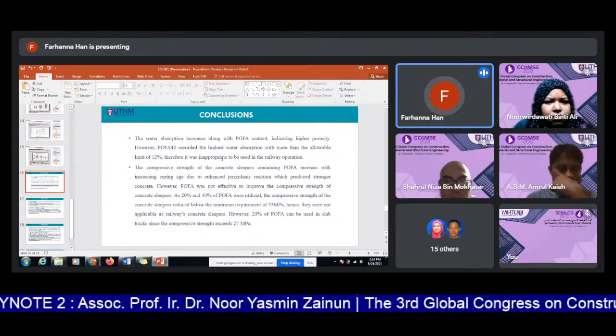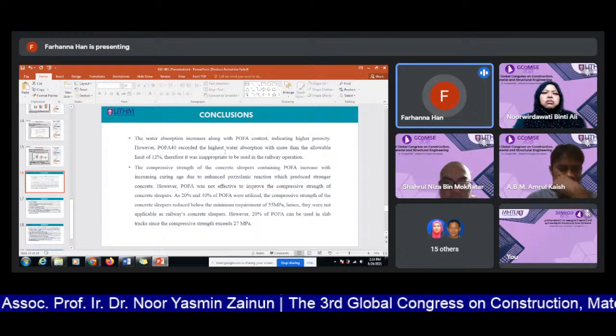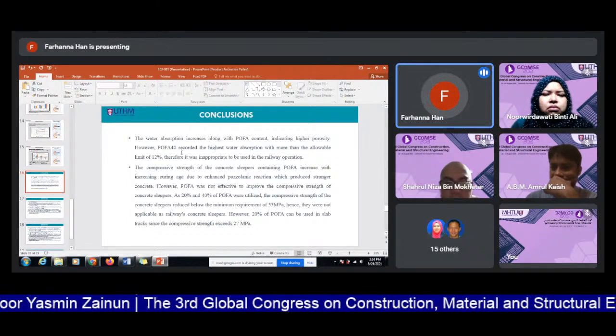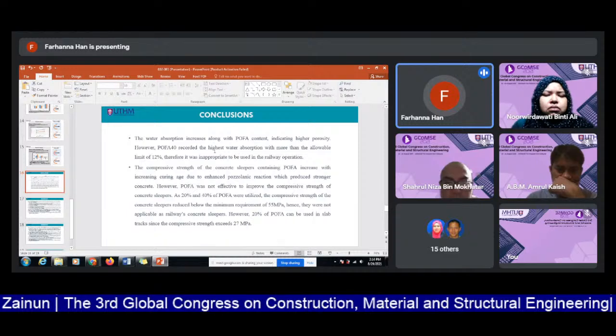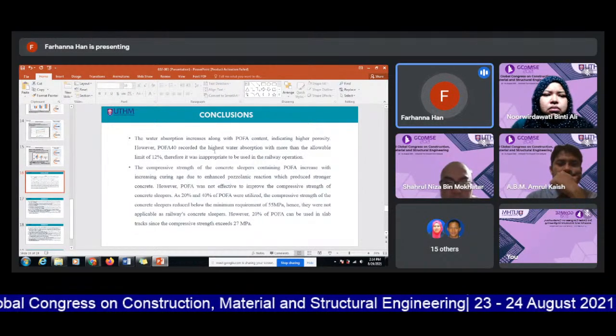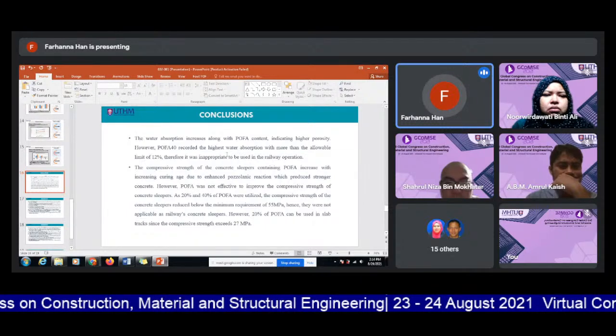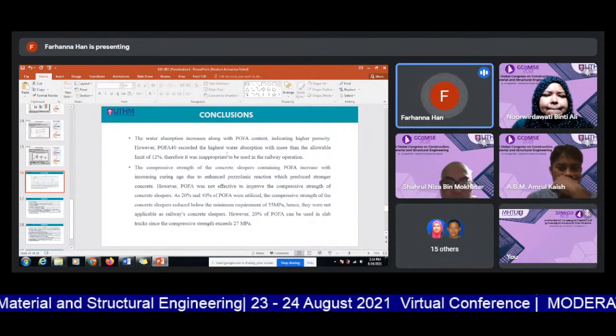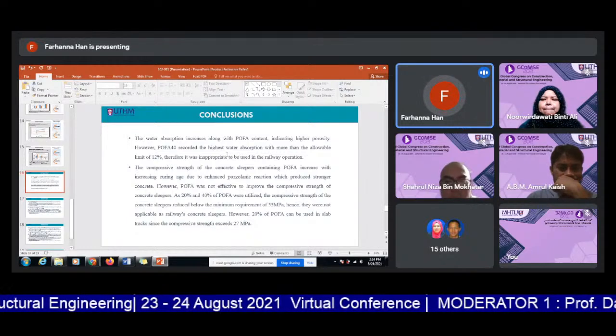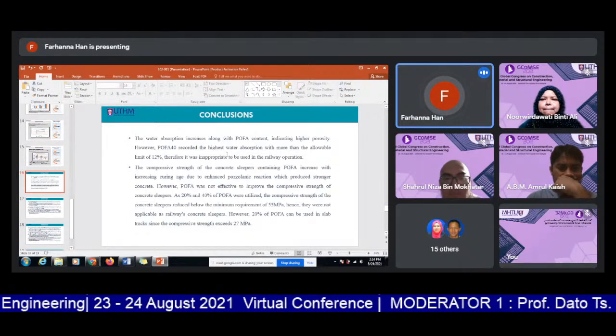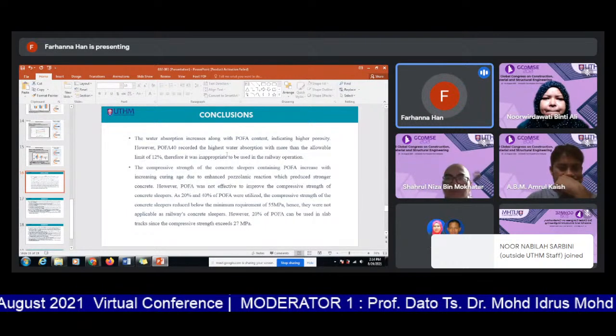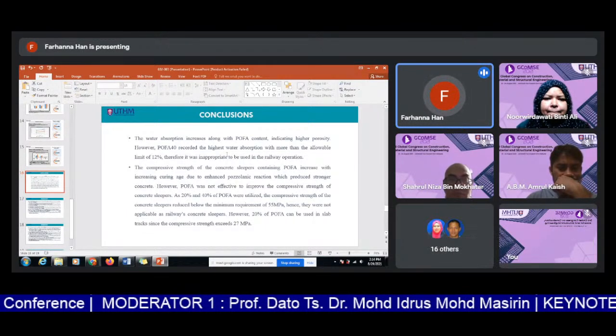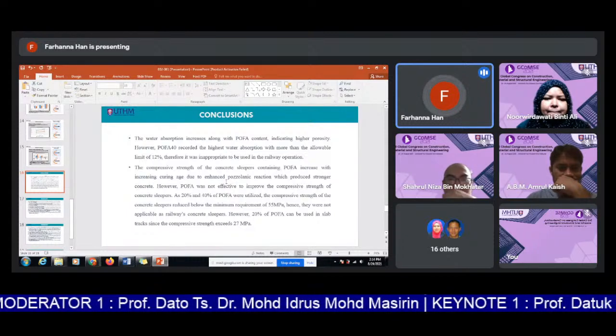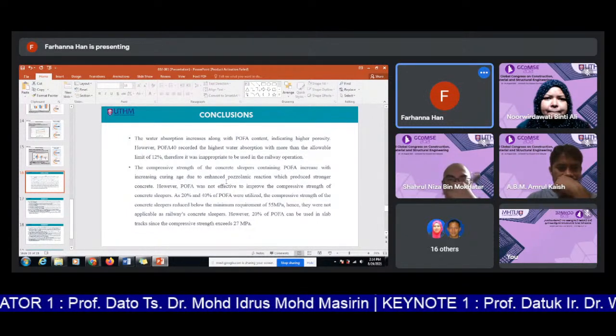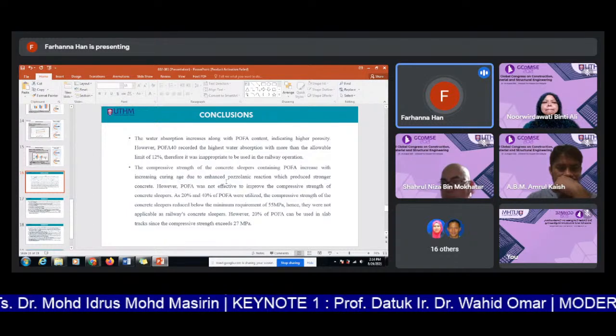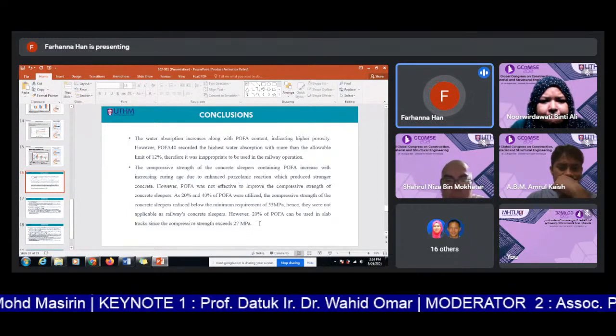As a conclusion, the water absorption increased along with POFA content, indicating higher porosity. POFA 40 recorded the highest water absorption, more than the allowable limit of 12%. Therefore, it is not allowed to be used in the railway operation. And the compressive strength of the concrete sleepers containing POFA increased with increasing curing age due to the enhanced pozzolanic reaction, and it produced stronger concrete. However, the POFA was not effective in improving the compressive strength. The compressive strength reduced as the POFA content increased, but the 20% of POFA can still be used as a slab track since the compressive strength is above 27 megapascal.